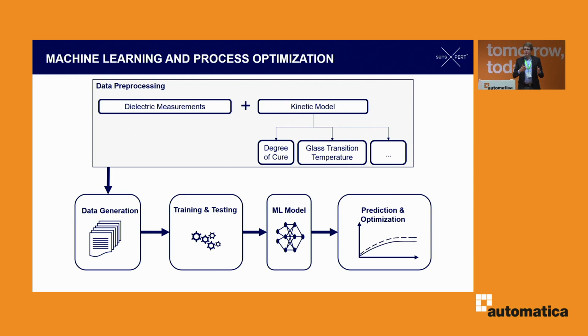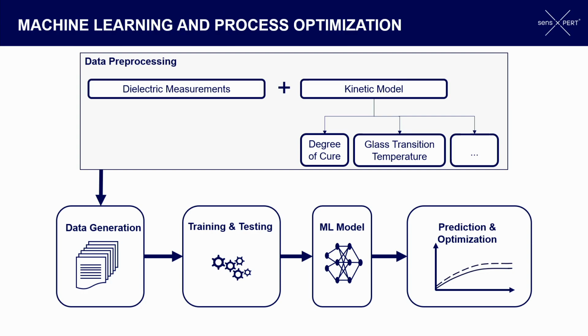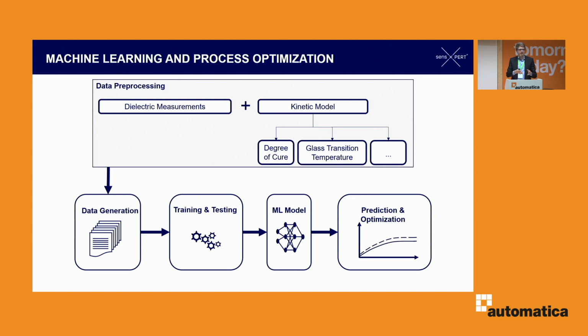And what we do with this measurement is we take the dielectric measurement data, we combine it with some material science, basically, so kinetic models and other information that we take from standardized lab experiments, and then we combine this into a machine learning model that has laboratory knowledge, material science, but also the real-time in-mold measurement that occurred during the production inside the mold. So we're really looking into the mold as the part is taking shape. And we combine this into a machine learning model that is then used for real-time process control.